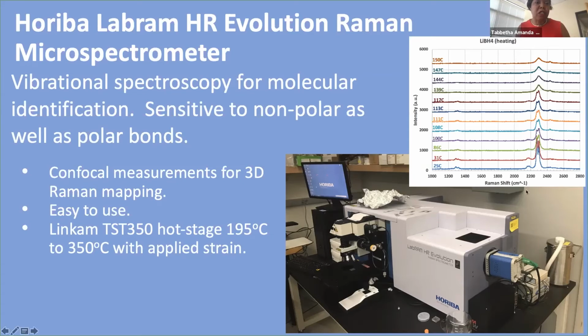particular bond type. So this is an example of lithium borohydride, and you can see that this peak here, if we were interested, we could actually find out the spatial region in our sample where this peak would be most prominent, and we can do that because it's equipped with a hot stage. We can do that to elevated temperatures. In this case, we're just showing you the spectroscopy, and we can see how this peak is changing as we elevate the temperature. So this hot stage goes up to about 195 degrees, and still you're able to do confocal imaging into the sample surface.